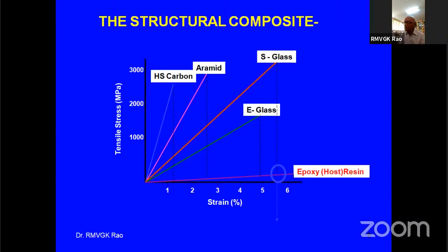What I want to show in this is that the slope of the curve shows the modulus, the stiffness, and the point where it ends, that line, is a breaking load. If you see, the S-glass has the highest tensile strength, followed by the aramid, that is aromatic polyamide, the Kevlar fiber, what we call yellow color fiber. Then carbon, some carbon fail also less than that. But if you see the slope of the curve, carbon has the highest slope, followed by aramid, followed by S-glass.